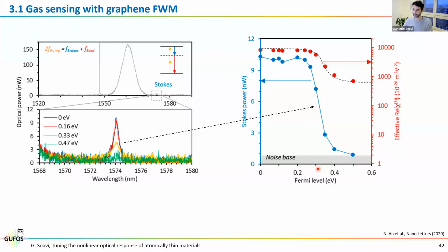But with four-wave mixing, the frequencies that play a role here are all very close to each other. It's between 1545 and 1560. So it's naturally phase matched because they all have the same speed inside. The dispersion is almost flat.